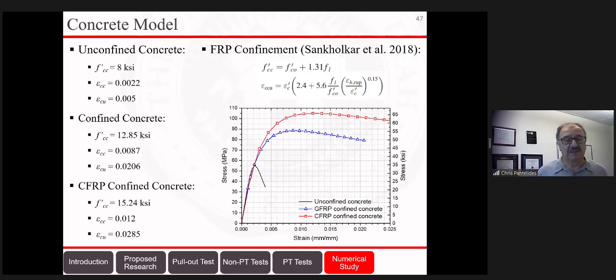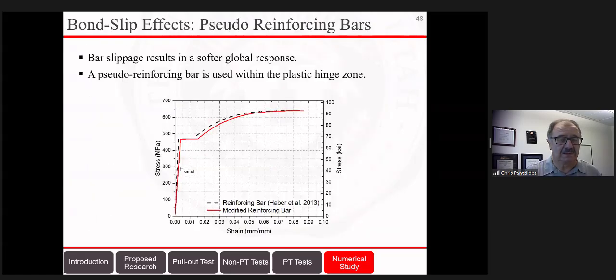So this shows the curves: unconfined concrete is the black. Blue is the fiberglass concrete, and the fiberglass concrete confinement is based on the model by one of my former students, Sankholkar, 2018, and you can find it in the literature. It's a pretty good model, a simple bilinear model. It works pretty well. And then the red one is the carbon fiber model. So using these models, we can capture the confinement properties of the concrete.